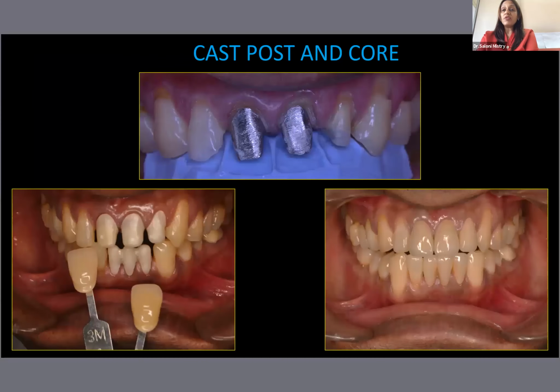Of course, when you have a fractured endodontically treated tooth and you have a ferrule which is maintained, then in such cases, it's always better to have. So this is the ferrule which is maintained all over, the 360-degree ferrule. My postgraduates will know, all our postgraduates, it's very important. This is the kind of zirconia coping which is masking the metal here of the post and core, cast post and core, and finally you have the crown here. So that's how you have to decide.